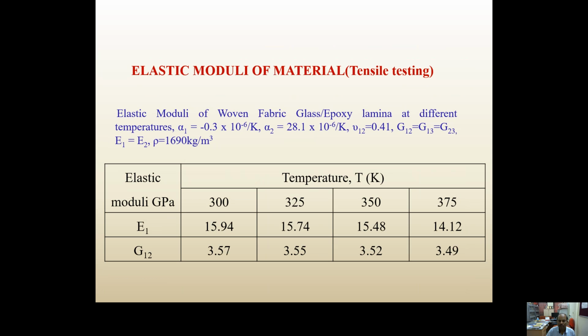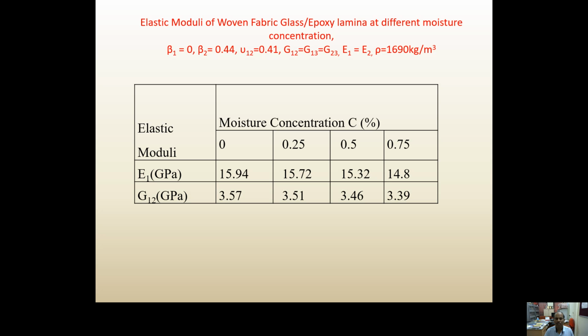The elastic moduli of the material found during tensile testing: E1 is 15.94, which gradually decreases to 14.12 with the application of temperature. Similarly, the shear modulus is 3.57 and gradually reduces to 3.49 by increasing the temperature from 300 to 375. Similarly, for the effect of moisture concentration, Young's modulus E1 is 15.94, reducing to 14.8 with the increase of moisture from 0 to 0.75%. Similarly, the shear modulus decreases from 3.57 to 3.39 with increase of moisture.